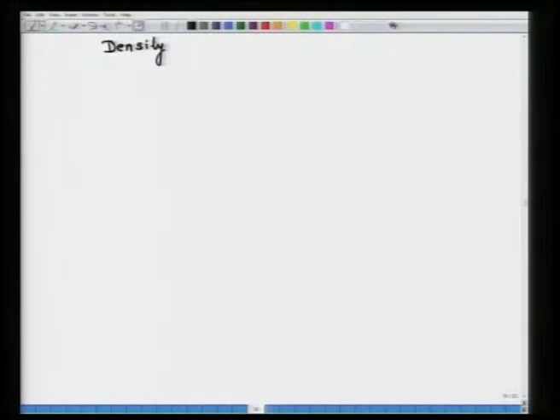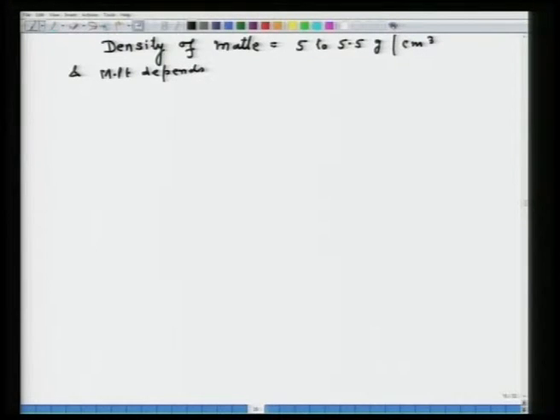Now, another important feature is the density of matte, which is equal to 5 to 5.5 gram per centimeter cube. The melting point depends on the proportions of Cu2S plus FeS, but normally for industrial grade matte, the melting point is between 1150 to 1200 degrees Celsius. So you can imagine this matte smelting is usually carried out anywhere between 1200 to 1250 or 1300 degrees Celsius, not higher than this temperature. This is what a matte is.